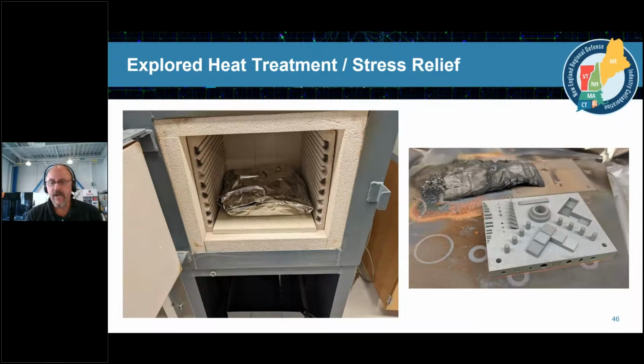So in 3D printing parts with the DMLS, the laser sintering systems at UMass and at CCAT, we requested a heat treatment system or process. Very simple: wrap it in tinfoil, throw in a small carbon source. In this situation, we used newspaper, and fire it at 1,000 degrees for about 15 minutes. Very simple process. Many companies work with this, especially if they're in the tooling industry. So that's the process we followed.